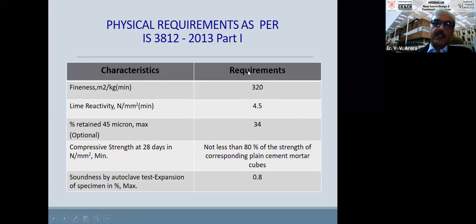Only specifically this can be supplied. But for the large quantity of fly ash we have, which is being supplied by NTPC, finding this 320 fineness, meter square per kg, is generally difficult. So there is a need for revision of this standard to reduce this to somewhere around 300. So this revision is also likely in the near future.